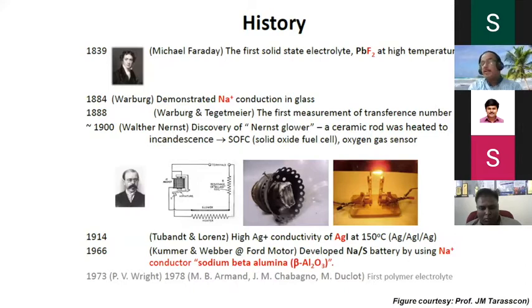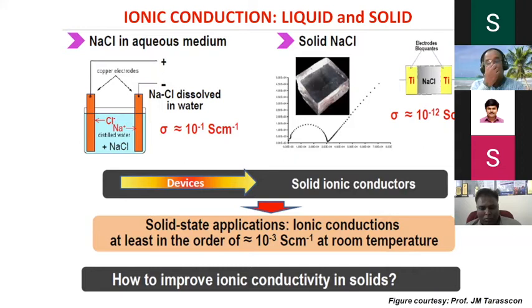1914 saw high silver ionic conductivity in silver iodide at 150 degrees Celsius. In 1966, a sodium sulfur battery using a sodium ion conductor, sodium beta alumina. Then in 1973, Wright made the biggest breakthrough, the first polymer electrolyte. So this tells very clearly: now we are living in the age of 2020, but solid electrolyte research started in 1839, just 39 years into the century. So it's not new to the world. From 1839 to 2020, we are struggling hard to find a good solid electrolyte to satisfy those conditions.